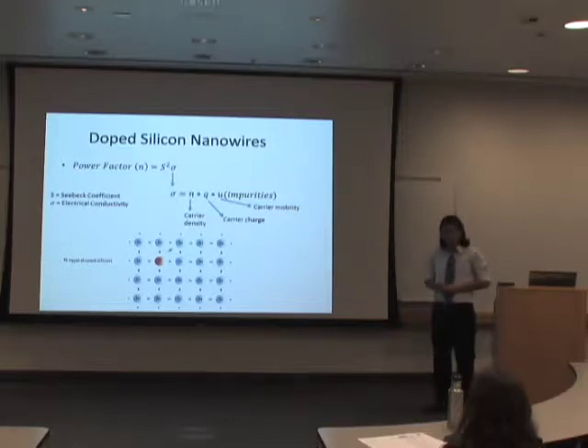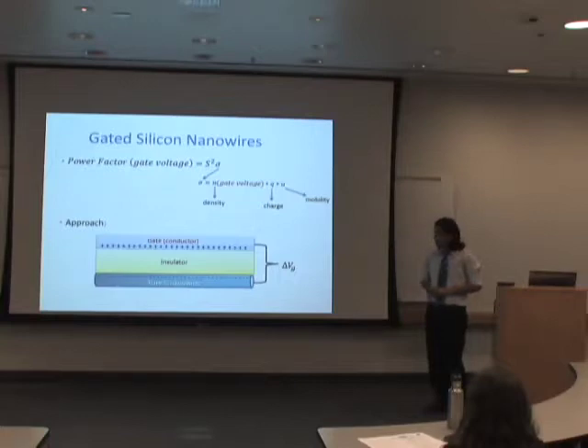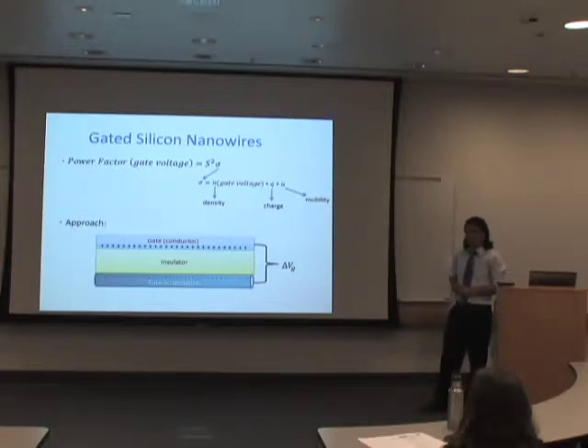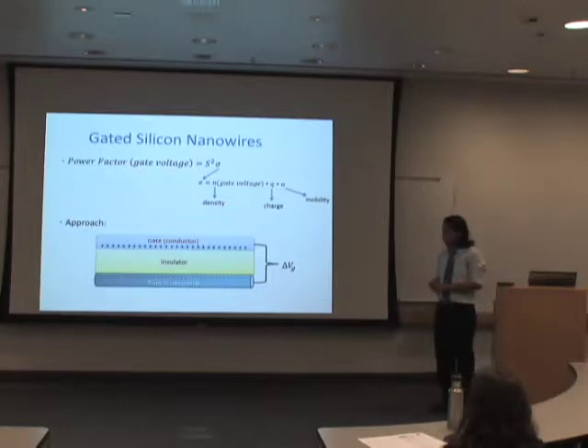So we're coming up with a new approach to find a way to increase its carrier density without having to add impurities, which increases the electroconductivity. Our approach is to have a pure silicon nanowire and a conductor, which we call the gate, with an insulator in between. It serves like a parallel plate capacitor. As you apply a voltage difference between the two, you're able to induce the desired carriers in your nanowire without having to add impurities. This allows us to increase the carrier density, which will now be a function of the voltage that we apply between the gate and the nanowire, without having to decrease mobility.